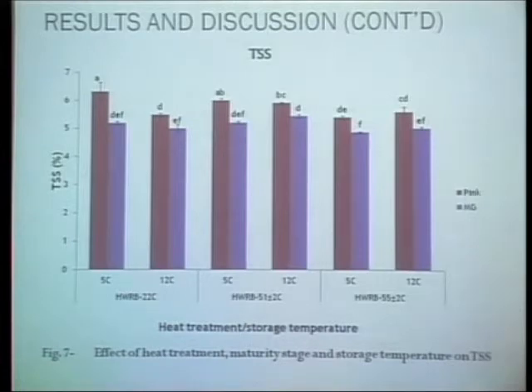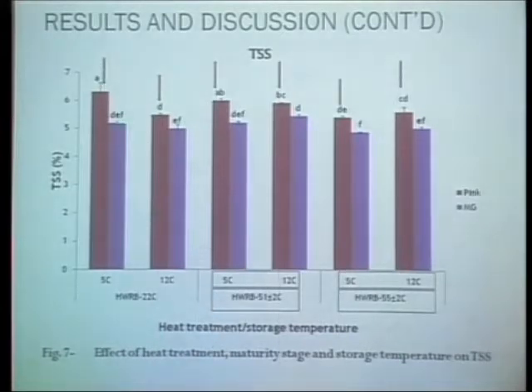Now, when we look at the TSS, the total soluble solids, we also didn't have any three-way interactions, but we noticed that for the maturity stage, the pink had a very high TSS, as you can see, after storage at 5 and 12. And the interaction was that at 5 degrees, even with this heat treatment, the TSS was very high in pink as well as in this heat treatment. And then at 12, the TSS was a little bit low under each of the treatments. Now, if we come to the control, we will realize that the TSS was very, very high. The reason being that at this stage, most of the fruit had ripened, and the TSS mostly increases according to the ripening process, as has been shown by the color development.